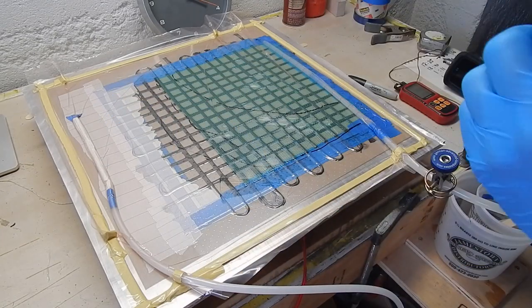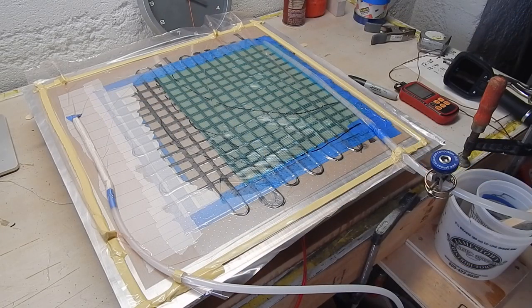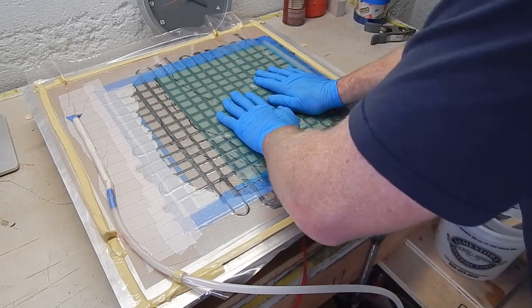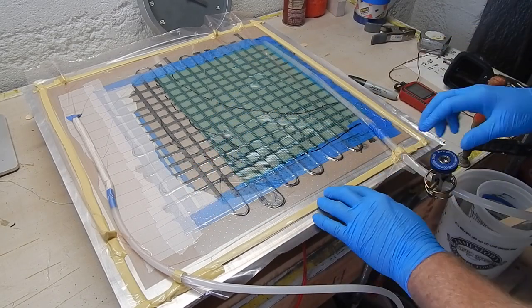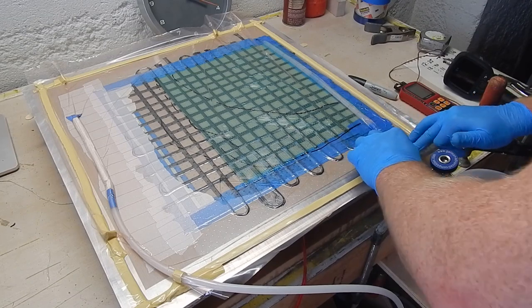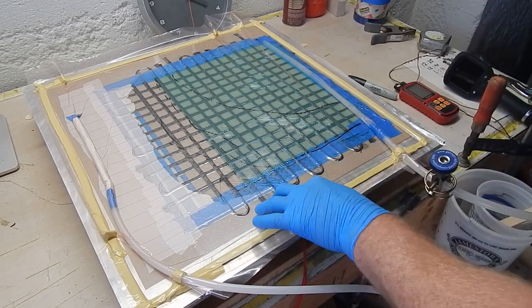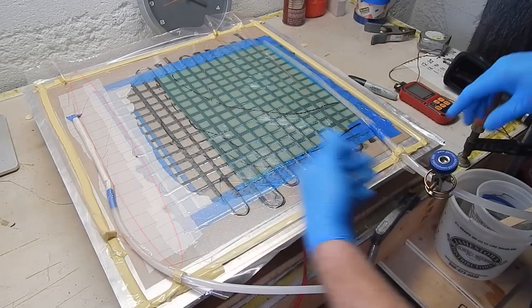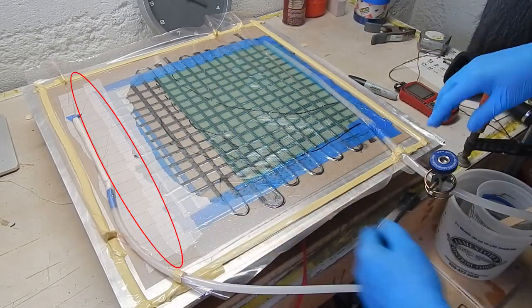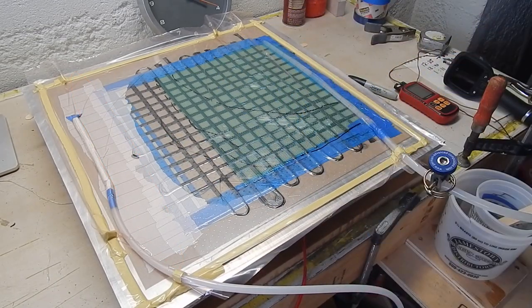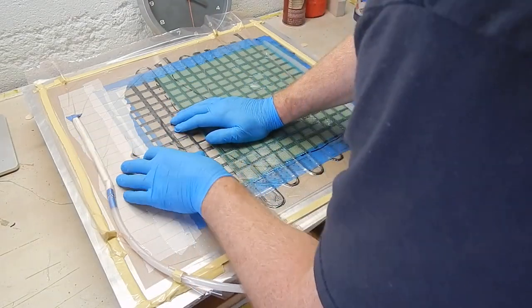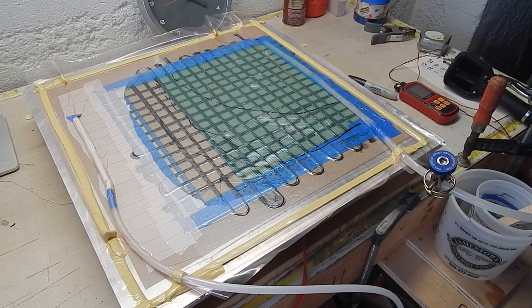Here I am clamping it off and making sure everything is tidy. No extra slack, no excess resin around the feed line. So it'll end up filling more. Now that it's clamped off, all the resin will equalize across the part. Having that vacuum break between the end of the panel and the MTI hose, which won't even get wet really, will just help keep any excess resin from feeding out of the laminate. So it's better to clamp it off early.